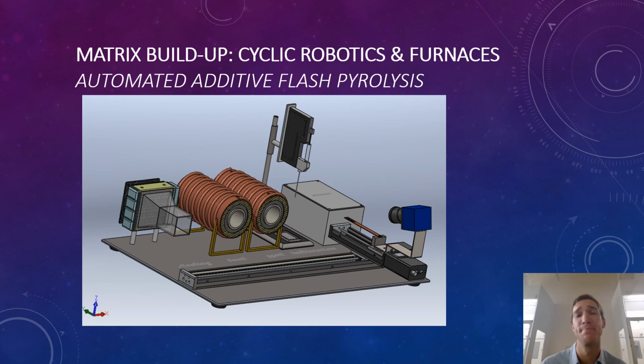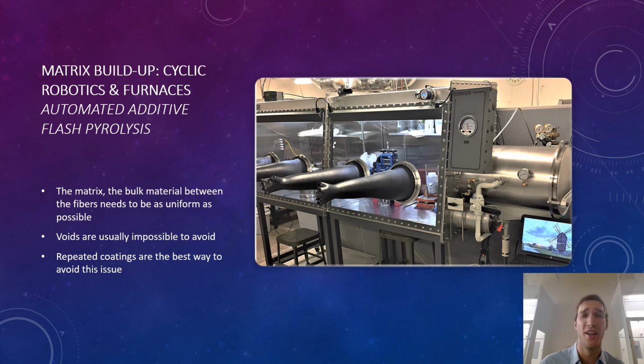And then a few pointers on this matrix buildup. We're looking at building up material in between the fibers by layer. So each layer deposits a very thin, within the sub-micron range, of ceramic residue, and then we're building it up layer by layer so that we don't end up with a lot of cracking in the matrix due to the shrinkage of the ceramic as it undergoes pyrolysis. Thus, the repeated coatings are the best way to avoid voids or cracks within the matrix due to that shrinkage.